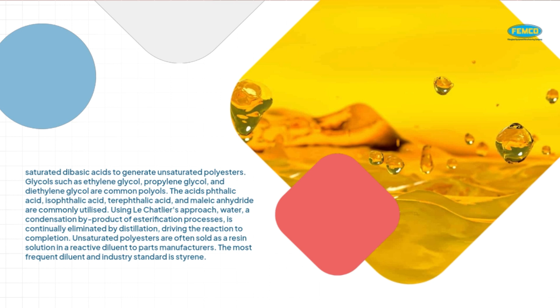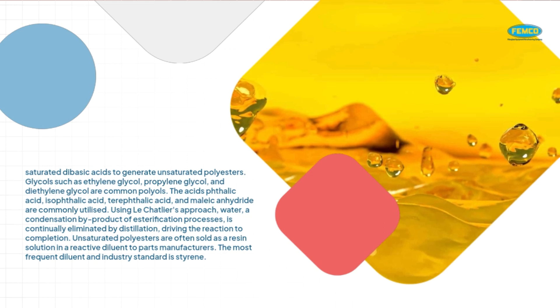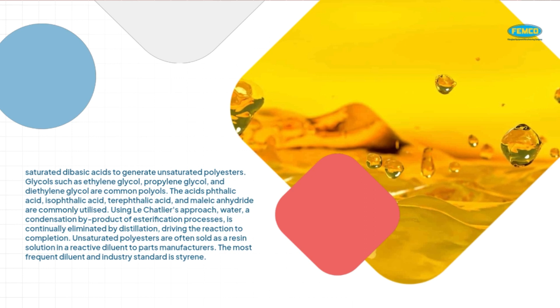Glycols such as ethylene glycol, propylene glycol, and diethylene glycol are common polyols. The acids phthalic acid, isophthalic acid, terephthalic acid, and maleic anhydride are commonly utilized. Using Le Chatelier's approach, water — a condensation by-product of esterification processes — is continually eliminated by distillation, driving the reaction to completion.